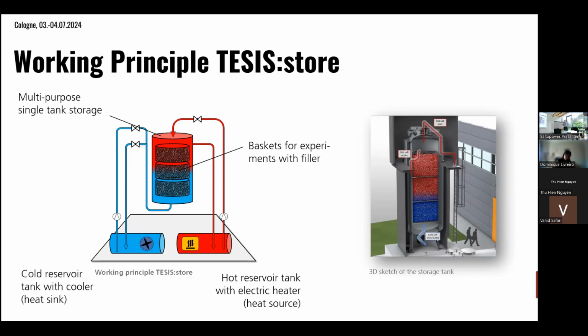And a feature of the plant is that we can have a pure thermocline in there, meaning we have only stratification of the salt just due to its density differences. But we can also test a concept where we have a filler material inside the storage tank, which has a total height of more than 5 meters. We can put the material inside 3 baskets we can stack on top of each other. This allows us to prepare everything outside of the storage tank, and then when everything is ready we can put everything inside the tank. It's a matter of a couple of hours and then we are ready to start testing.